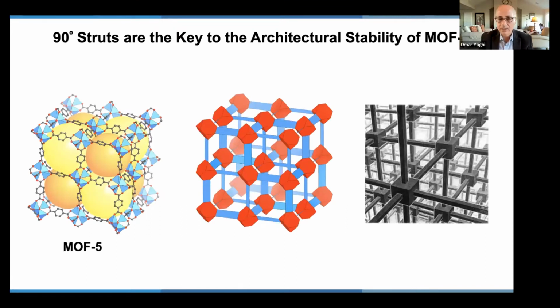But I would just want to advance the idea and show you that in MOF 5, we have achieved this vision of exposing every single metal atom by having these metal oxide linkages linked by organics. And the reason MOF 5 and other MOFs are architecturally robust is that you can see many 90-degree interactions where your linkers are turned 90 degrees to each other, just like, let's say, struts in a building. When you're making a building, you're trying to maximize the number of 90-degree interactions, whether they are the adjacent 90 degrees like this or turning one rod with respect to another. That makes a very stable architecture. That's why MOF 5 is an incredibly architecturally stable material.